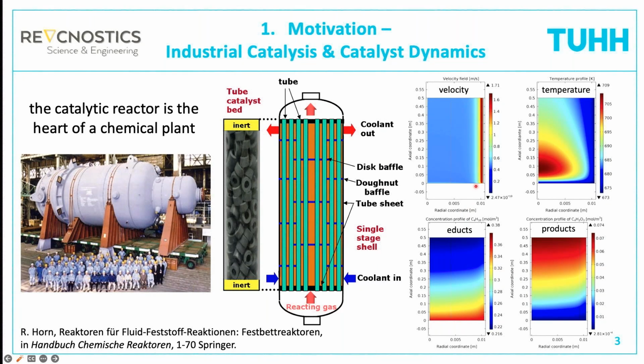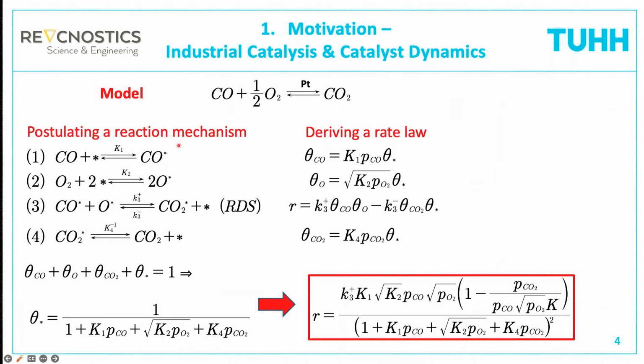And to understand this, we have to take a look how simple this model is that is behind such a simulation. And here I want to take an example that I will show you also later in the talk. This is CO oxidation on platinum, where we can derive such a model very easily. So the first step is we have to postulate a reaction mechanism. We normally don't know in catalysis how the reaction occurs at the atomic scale on the surface of the catalyst, so we have to postulate a reaction mechanism. And we also don't know on which active centers this catalytic reaction takes place. So we typically write a little star to symbolize an active site.